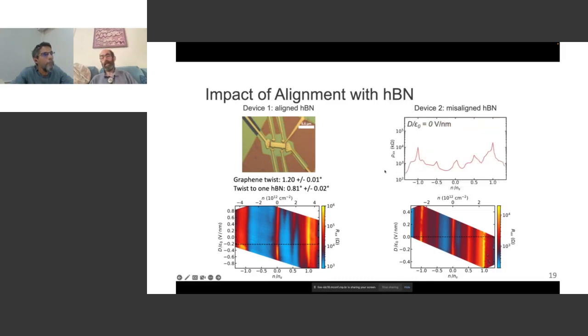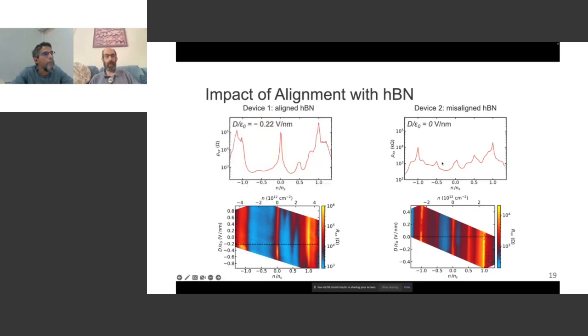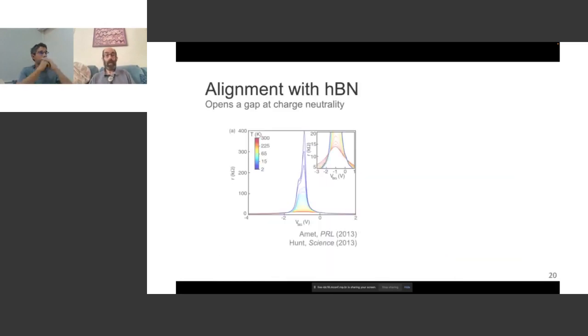Here for the misaligned case, you can see that there's a resistance at the charge neutrality point of 2 kiloohms or so. That's very typical for graphene. But here it goes up to 100 kiloohms. So as I mentioned, it was a much higher resistance. Also you can see features not only at full filling, but at somewhere beyond full filling, near there. And these turn out to be associated with the pattern made by graphene and HBN, hexagonal boron nitride. They too make another moiré pattern. So there are some things that are different.